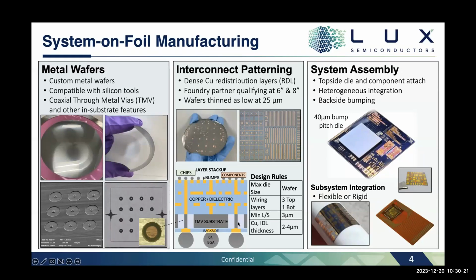Another feature that would be required when using a metal substrate is not so much a through metal via, but just the elimination of all the metal that is underneath or above a large ball or bump, so that you don't get any capacitive coupling between a bump and the metal substrate itself. There are a variety of features. We don't show this one here, but you can imagine a hole is drilled through the substrate, filled with dielectric, where the bump is going to be placed. So locally, the bump will see a glass substrate, and then you'll pattern an RDL layer on the bottom to connect that bump with another portion of the substrate that has a through metal via.